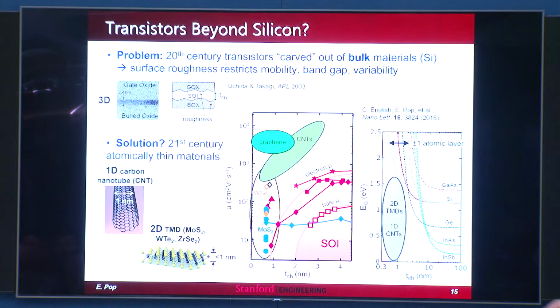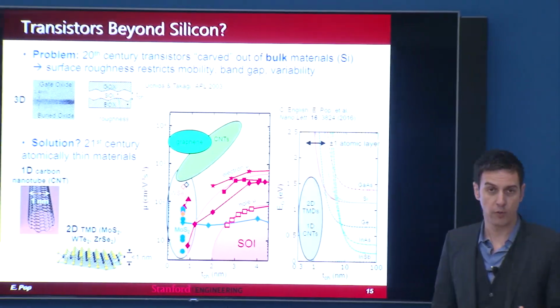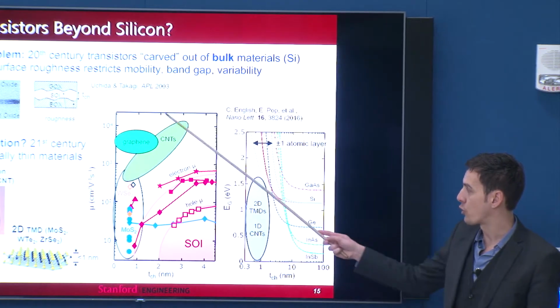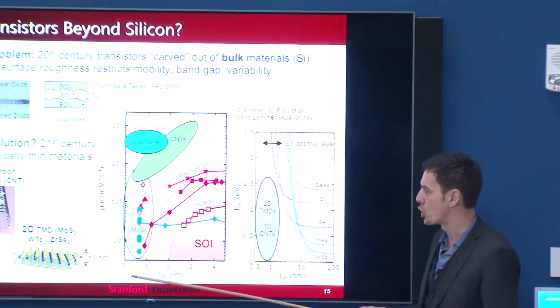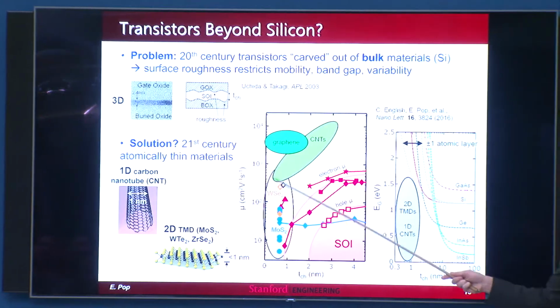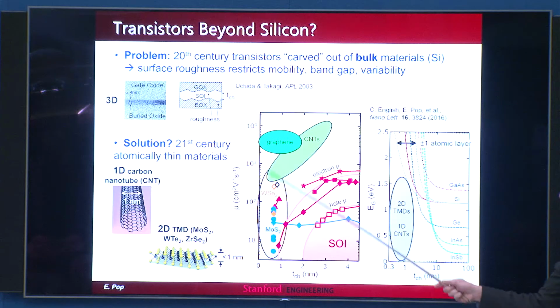So that's where what Philip and I call 21st century atomically thin materials could fit in, at least transport-wise. Of course, there are carbon nanotubes and 2D materials, both fit in the same place. Graphene and carbon nanotubes have good mobility. That is a function of thickness, a function of diameter, but it's good in general. And then some of these materials have larger band gaps, but they also have pretty decent mobilities for the thickness regime that is very difficult to touch with bulk materials, certainly with bulk silicon. The band gaps, by the way, also change quite a bit when you take these materials and confine them into quantum wells. And again, if you need a decent band gap of 1 to 2 eV at these thicknesses, then you're probably in pretty good shape working with some of these materials.